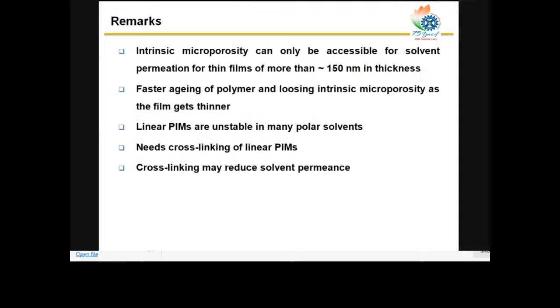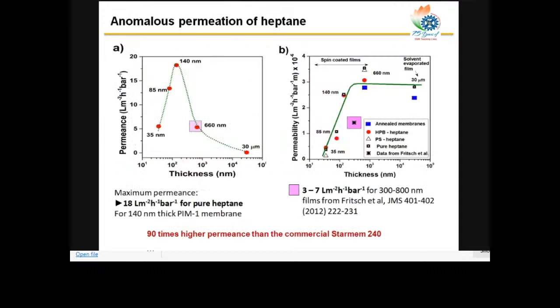On the right, if you see the graph, this green line, I'm plotting thickness versus permeability. Permeability means the liquid permeance multiplied by its thickness. To a certain extent, this permeability remains constant. If you decrease the thickness, the permeability goes down, which is the same thing I just explained: the permeability of the material is not constant. That means below a certain thickness, the material is getting a different porous structure, or the porous structure is being lost. However, we get 90 times higher permeance compared to the commercial Starmem 240, and this was still higher than the commercial membrane.